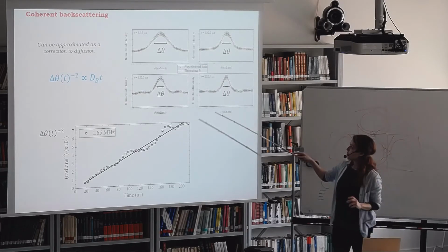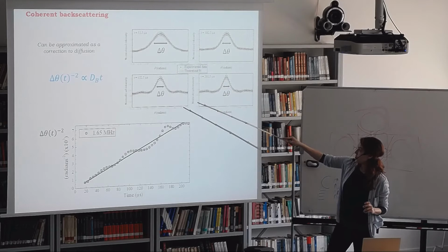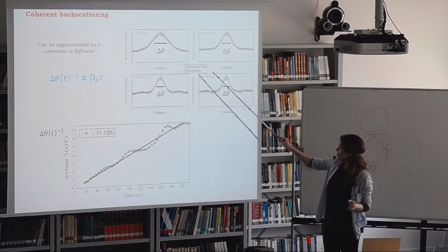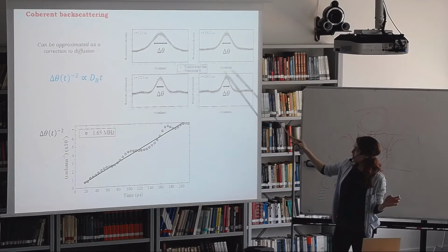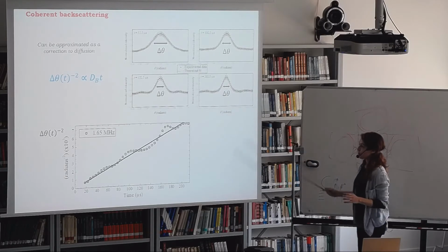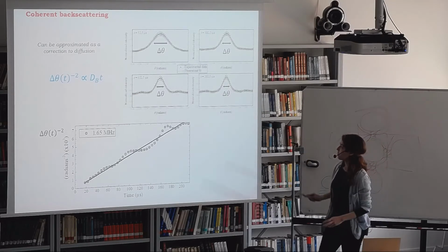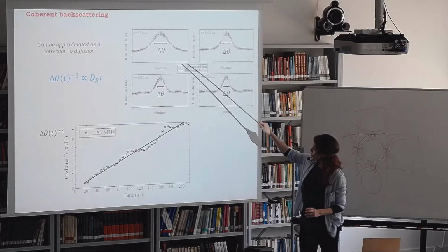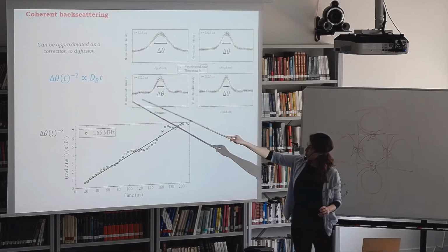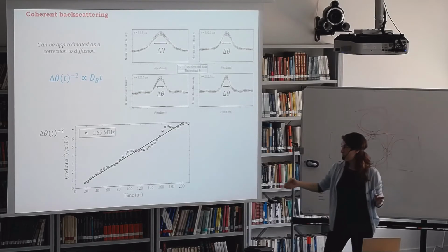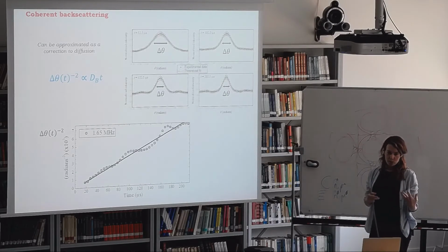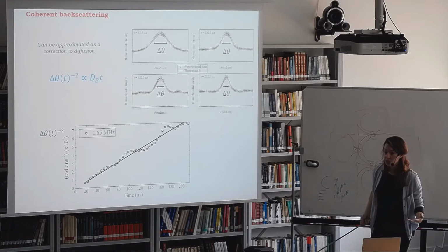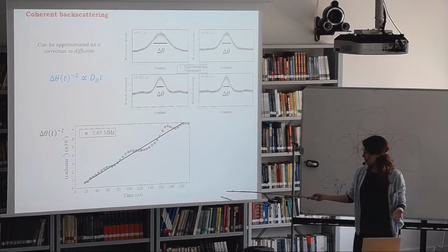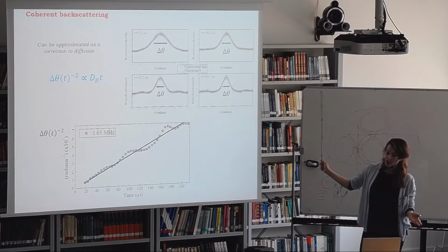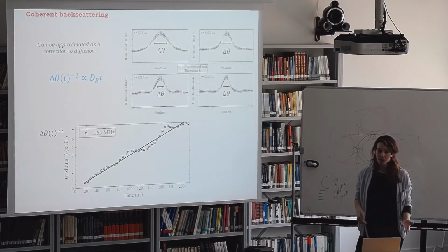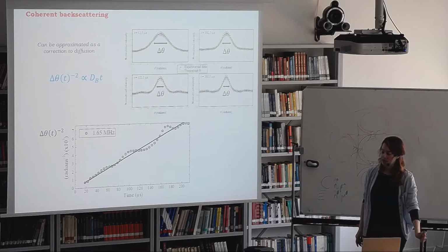So here we see the normalized intensity as a function of angle between source and receiver for different times. So you can see that the cone narrows as a function of time. And the theory now tells us that this narrowing, 1 over the width of the cone squared, is proportional again to time times the diffusion coefficient. So in analogy to what we saw in transmission, just like in transmission, we can plot this quantity as a function of time. So we get a nice linear curve. And we can use this again to measure the diffusion coefficient if we want.